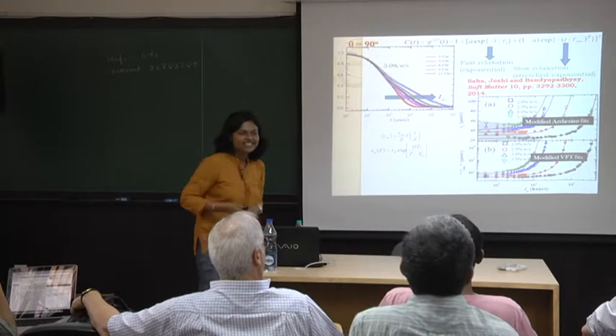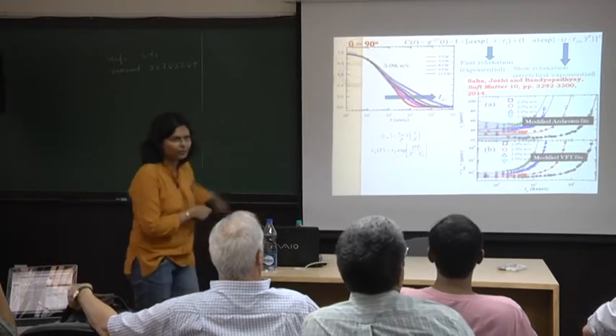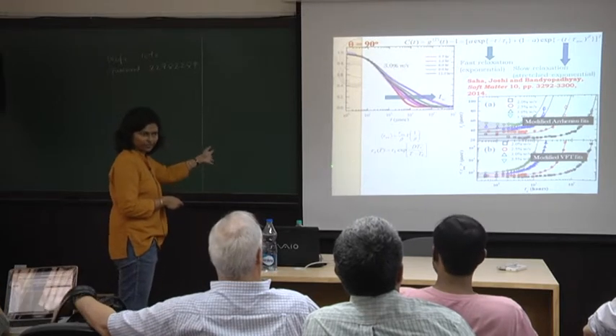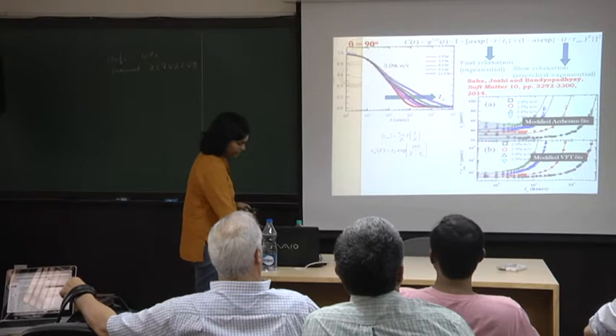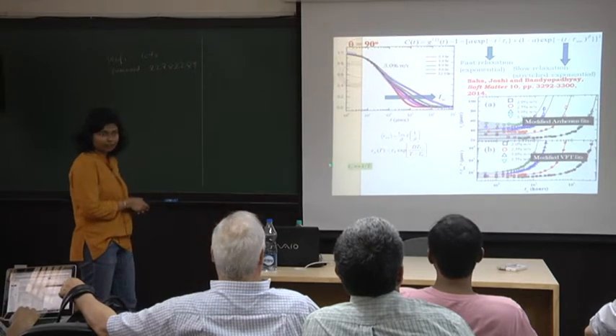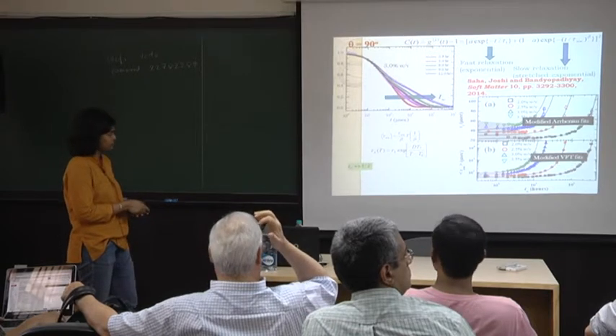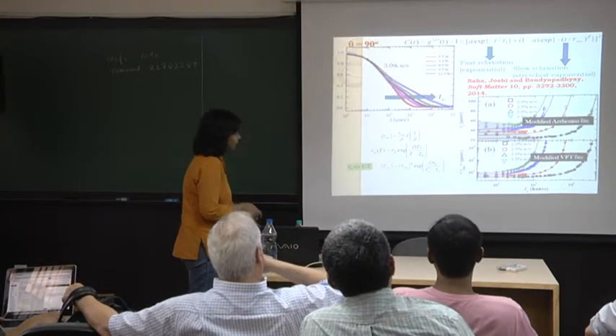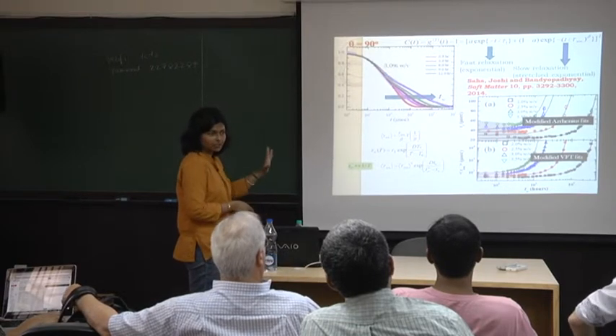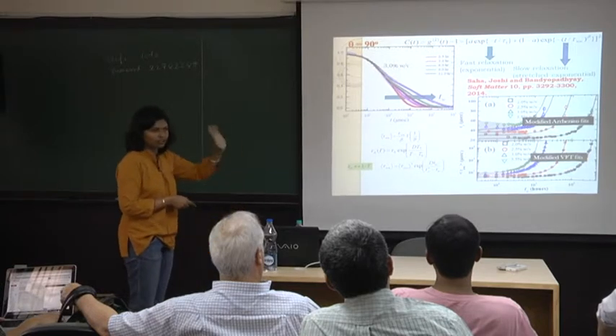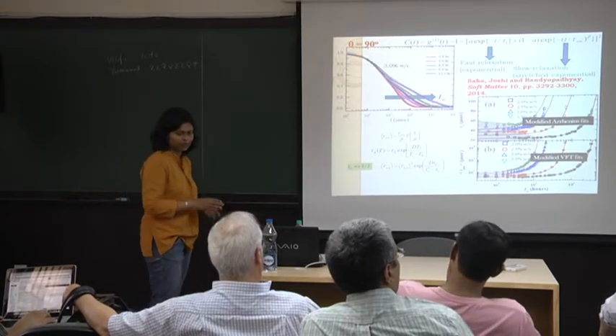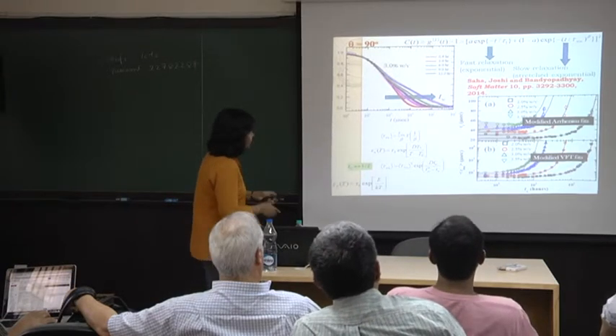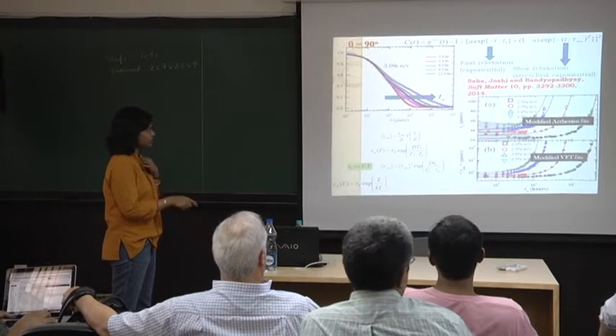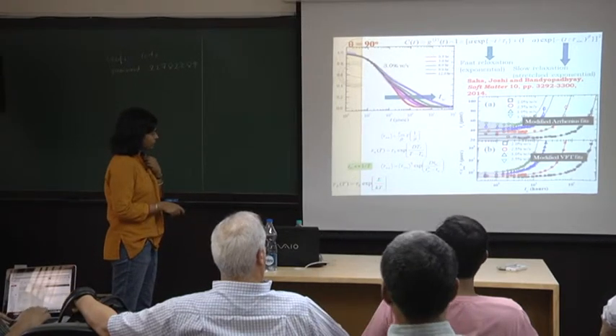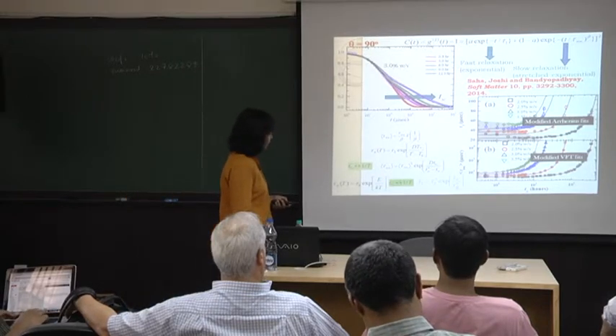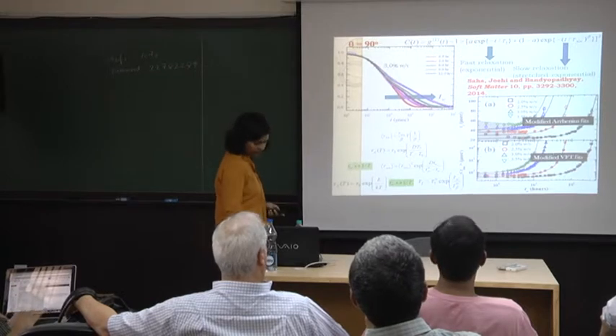Sorry? So that is our own nomenclature, I was coming to that. This is what we've always done for supercooled liquids, right? All we've done here to get our modified forms is substitute the inverse of the thermodynamic temperature with the age of the Laponite suspension. We've ended up with a form like this, and these are the black lines that you see here. It does well for the slow relaxation time, not so well for the fast relaxation time, but like I said, I'm not going to go back to that. You can do something similar with the Arrhenius form, which is the fast relaxation time. We've just substituted 1 over T by the age of the system, and these are the black lines that we get.